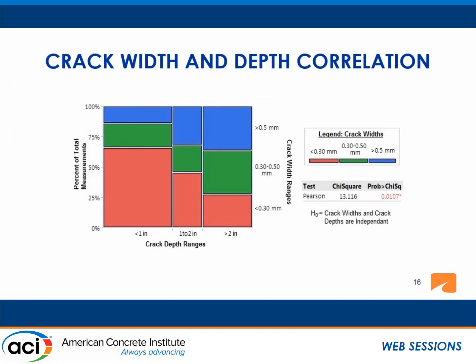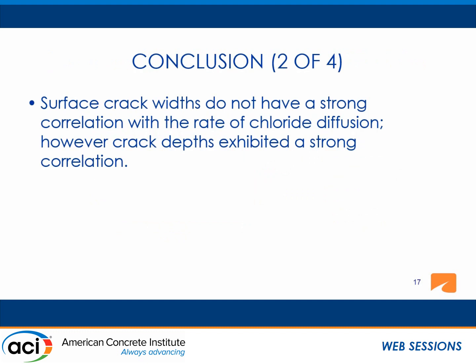So we wanted to see if there was any dependence between the crack widths and crack depths themselves. This is an independence plot. And as you can see, there is a small correlation going on. However, the results showed that it was really weak. The R-squared value was about 0.06. So there's not a significant correlation between crack widths and crack depths. So that's our second conclusion.